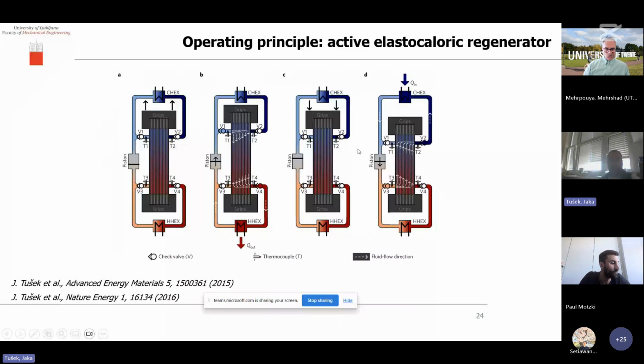So almost 10 years ago now, we designed and tested the first active elastocaloric regenerator. And here are the 4 basic operational steps and the schematics of such a system. Here in the middle is the elastocaloric regenerator in the form of thin sheets, which are clamped in the grips and then connected to the actuator. It's also connected within the hydraulic system to heat sink and heat source, which are here hot and cold heat exchangers. And we also have a piston pump to pump the fluid and 4 check valves that control the fluid flow.